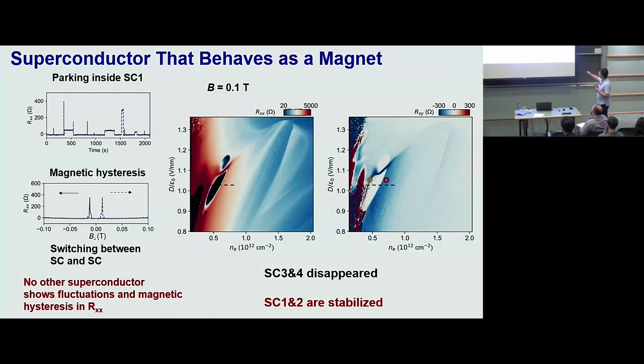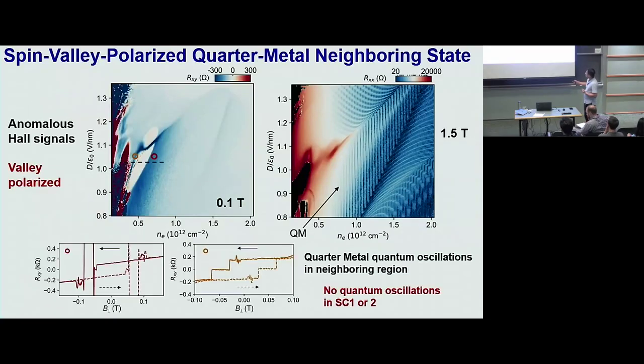And you can anti-symmetrize the Rxy channel to get the Hall signal, okay? As you can see in this bluish region, you have a lot of anomalous Hall resistance. Even to the left of this superconducting state I call SC1, there is a blue stripe that shows anomalous Hall, okay? And that anomalous Hall resistance is real. It's really anomalous Hall because if you do magnetic field sweep, there is hysteresis, both to the left and to the right, okay? So there's valley polarization. The 2 valleys are time reversal pairs of each other. If they're equally populated, anomalous Hall resistance is supposed to be 0. But here, you have anomalous Hall, so valley is polarized.